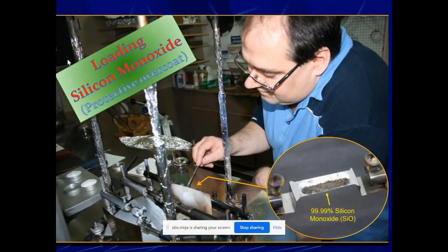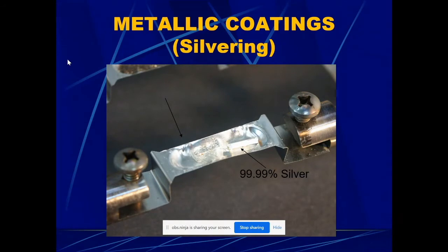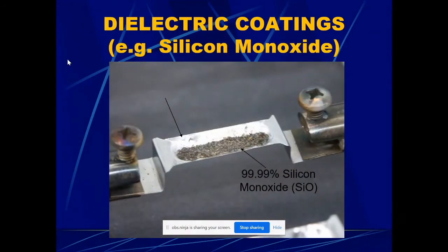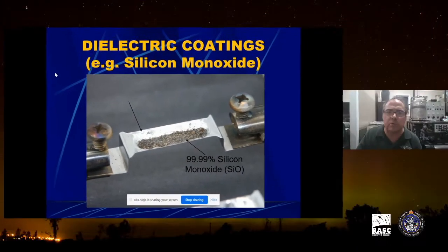Here's another example of a silicon monoxide boat. You can do silver in here as well. Silicon monoxide is sometimes used as a protective overcoat. I don't recommend it because silicon monoxide takes a long time to naturally oxidize in air, and it also reduces the reflectivity of aluminum even more than 87%. So the enhanced coatings are the way to go.